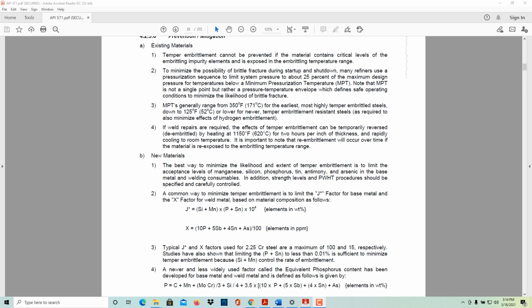In addition, strength levels and post-weld heat treatment procedures should be specified and carefully controlled. A common way to minimize temper embrittlement is to limit the J factor for base metal and the X factor for weld metal, based on the material composition as follows. J equals (silicon plus manganese) times (phosphorus plus tin) times 10 to the 4th power, with elements in weight percentages. Elements in parts per million would be your X factor: (10P plus 5Sb plus 4Sn plus As) divided by 100.